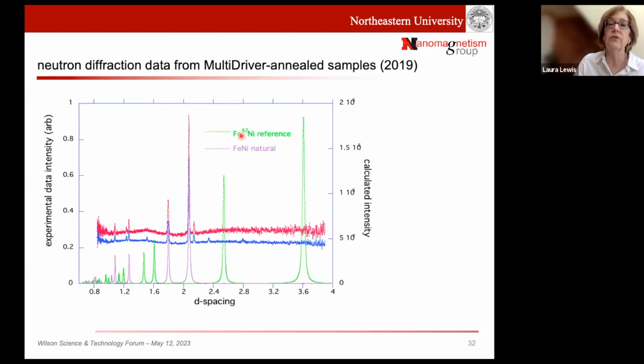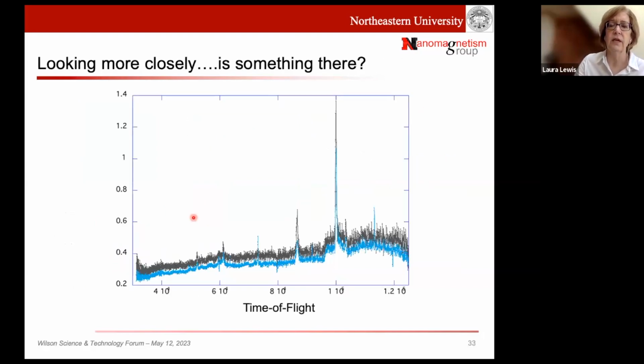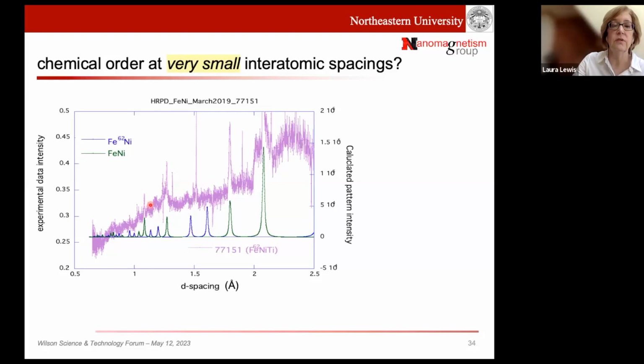And at first look, what you're seeing is, this is our nickel 62 reference. The data are red and blue. And I was hoping I would see peaks where these green ones are. And unfortunately, I don't. And I was really disappointed, but I don't give up easily. And I thought, well, wait a minute. I don't think there's something there, but maybe if I go down and really zoom in, I see these oscillations. I'm like, what is that? So when I match up the oscillations with the anticipated data, it looks like there might be something there. It looks like we have a very, very low level of atomic order.